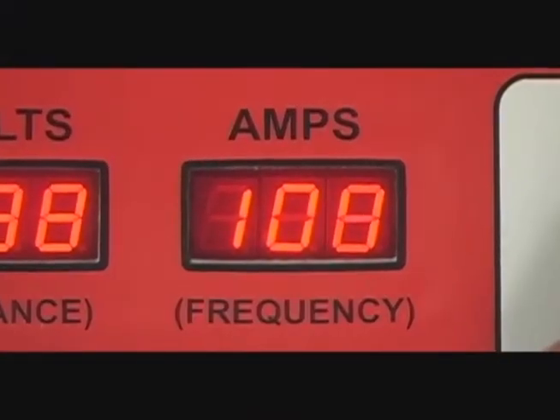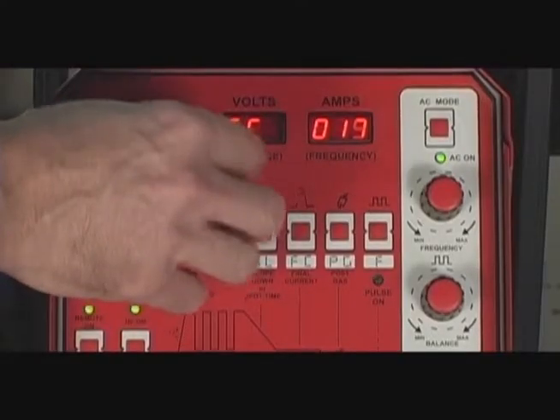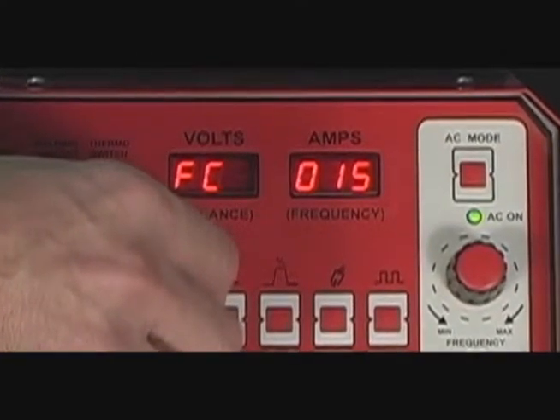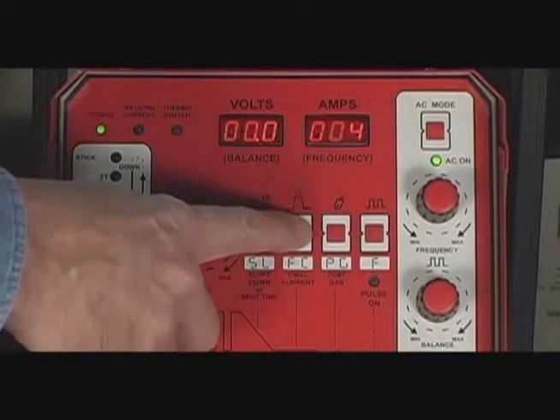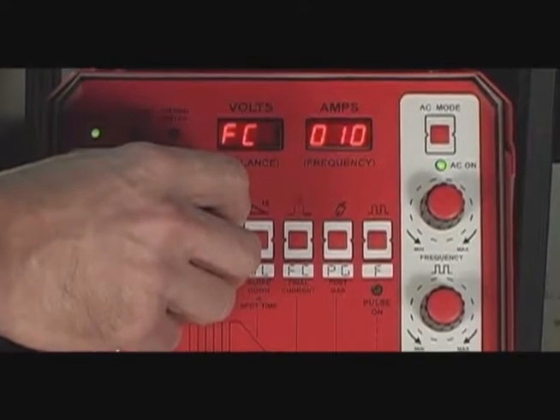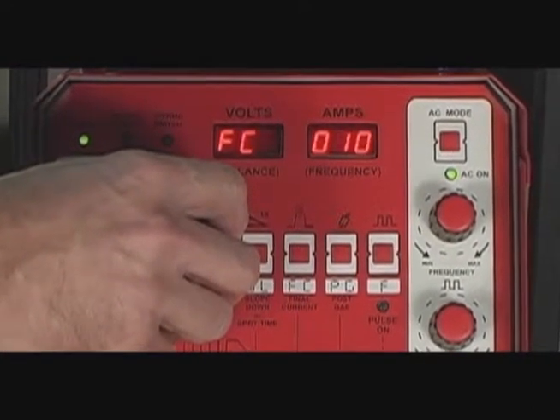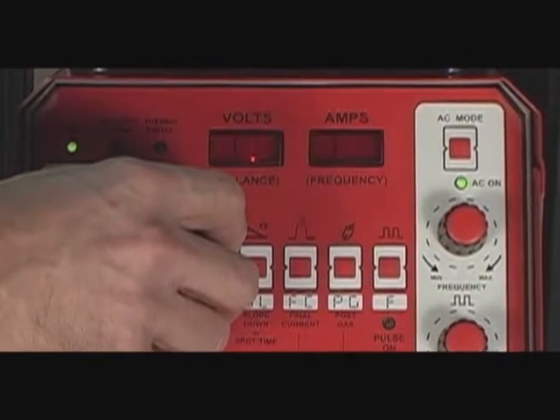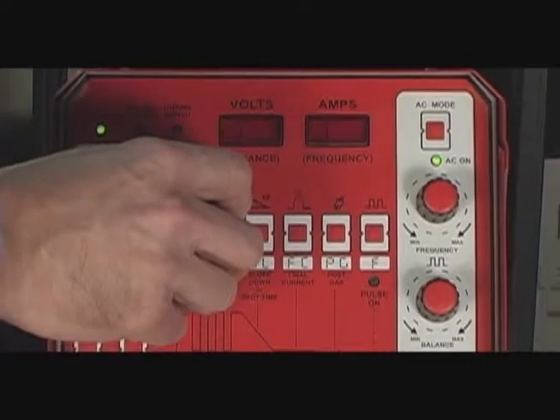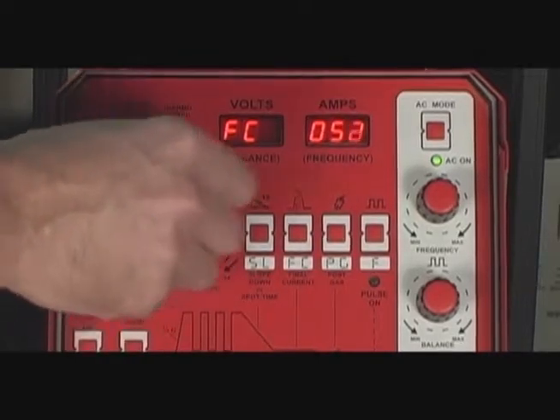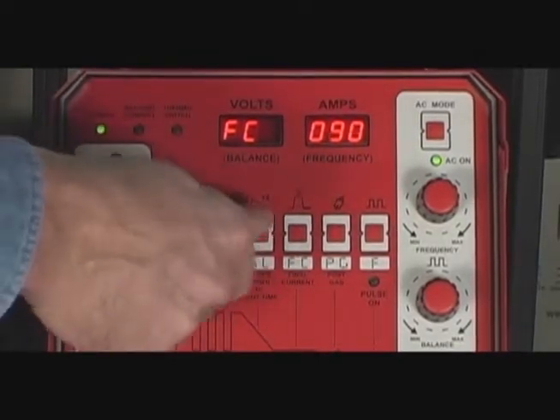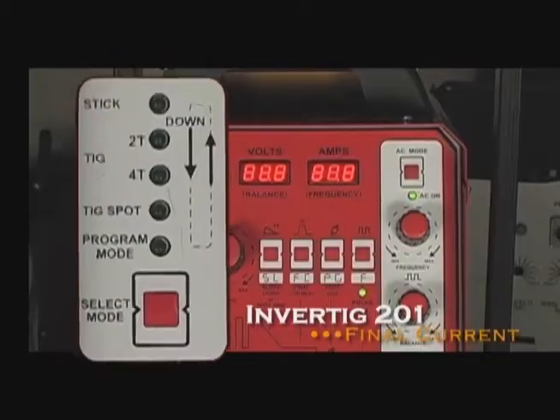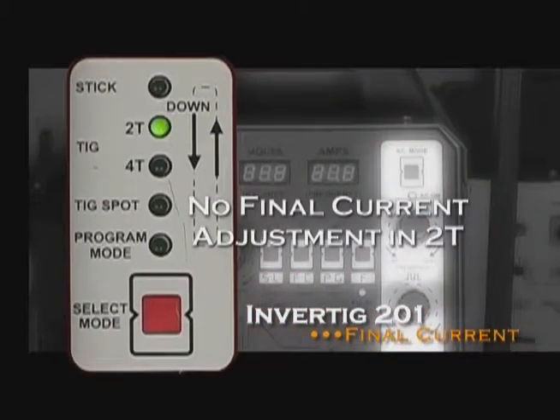knob. For example, if the amperage adjustment knob is set to 100 amps and the final current is set to 15%, the final current is 15 amps. To adjust the final current, depress and release the final current button. The volts display will flash FC for final current, and the amps display will flash and display the final current in percent. While both displays are flashing, adjust the amps knob to set the final current in percent to the base current. Remember, there is no final current adjustment in the 2T mode, since this is controlled with the pedal.